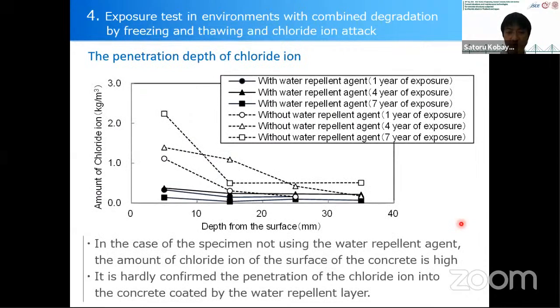So this is the test result of the penetration depth of chloride ion. White is without water repellent agent. Black is with water repellent agent. 1 year, 4 years, 7 years exposure. In the case of the specimen not using water repellent agent, the amount of chloride ion at the surface of the concrete is considerably high after 7 years of exposure. But it is hardly confirmed that the chloride ion penetrated into the concrete coated by the water repellent layer, like this.